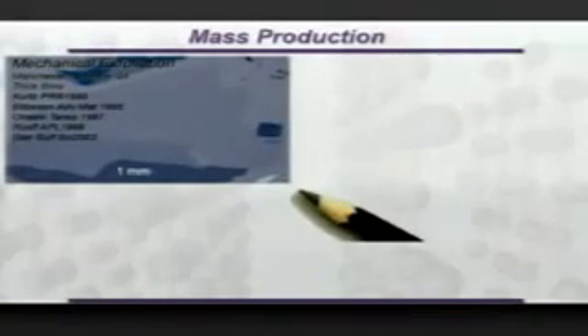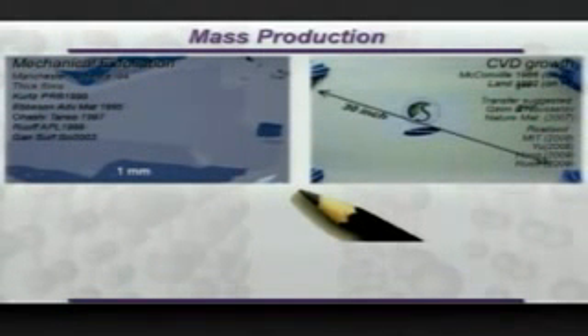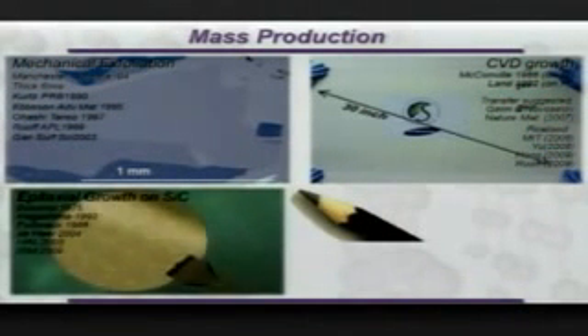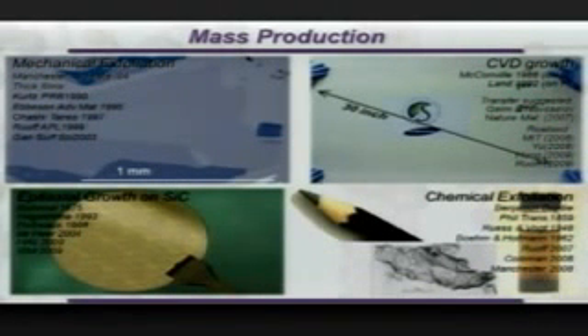Luckily, there are now a few other methods to produce graphene, and we can indeed produce 30-inch pieces of graphene, which are enough for any applications, and you can indeed use it for realistic applications. There is the so-called CVD method. There is epitaxial growth on silicon carbide. For composite materials, you can use liquid phase exfoliation. So this problem is more or less solved now. We can get large quantities of graphene quite cheaply nowadays.